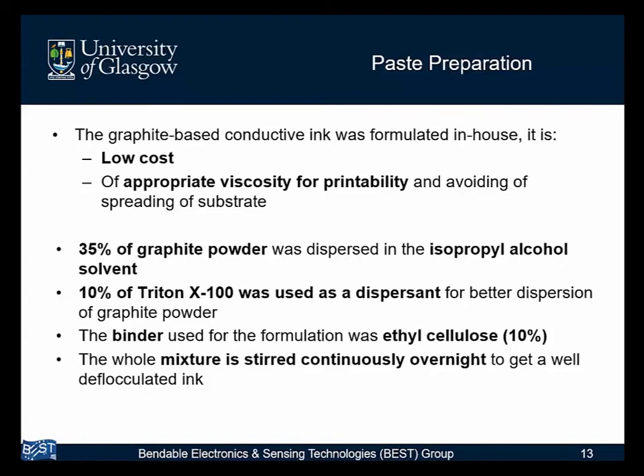Primarily components of graphite powder and isopropyl alcohol as a solvent, which we've experienced gives us some good printability. We've added a dispersant as well, Triton X100, for better dispersion of the powder. But we've also added a binder of ethyl cellulose to better bind the conductive particles together during printing. The mixture is obviously still stirred continuously to get a homogeneous ink, to allow the dispersion of the graphite powder.